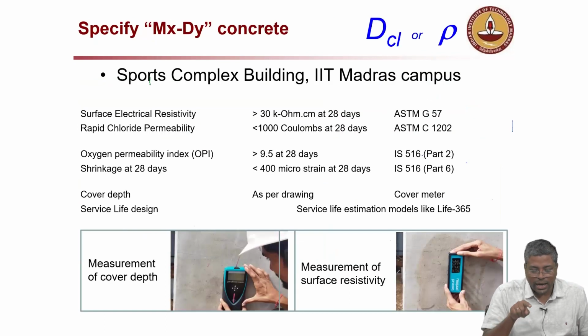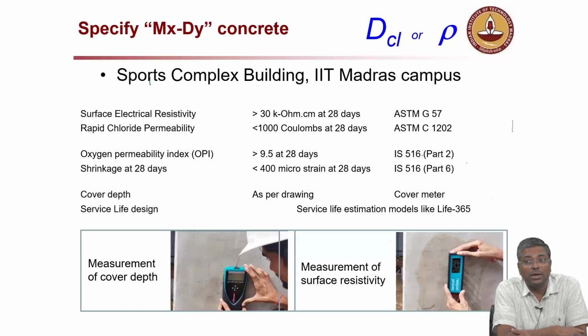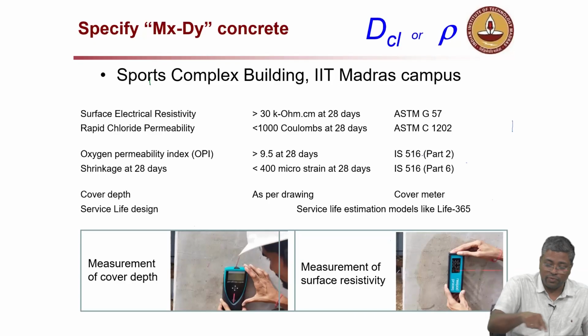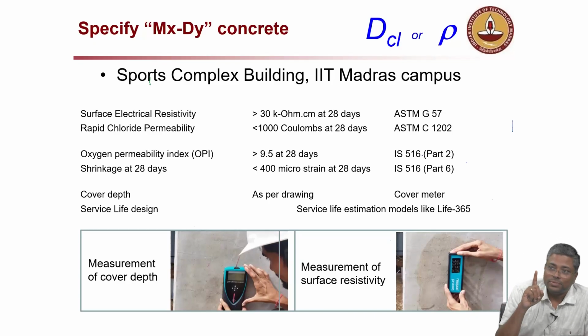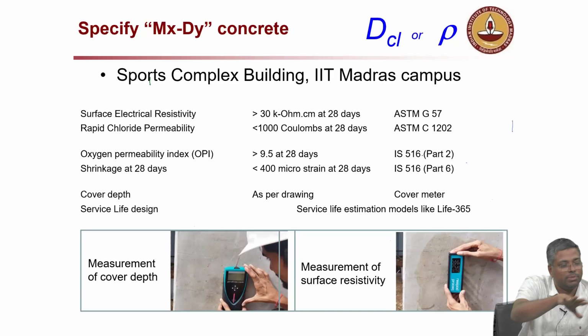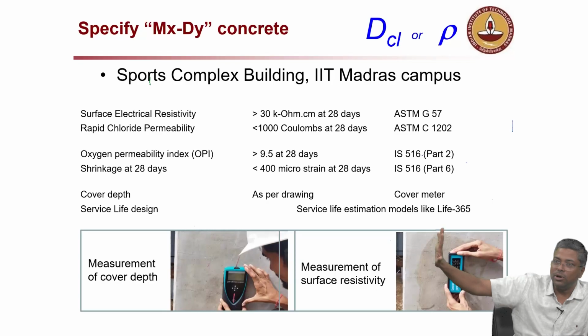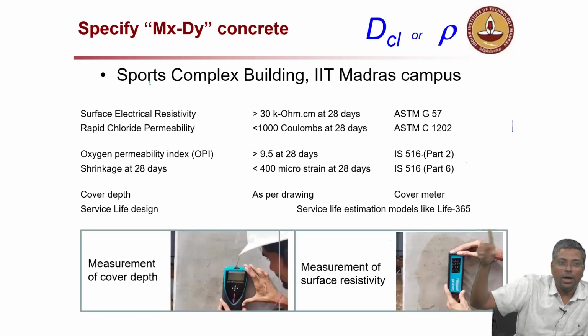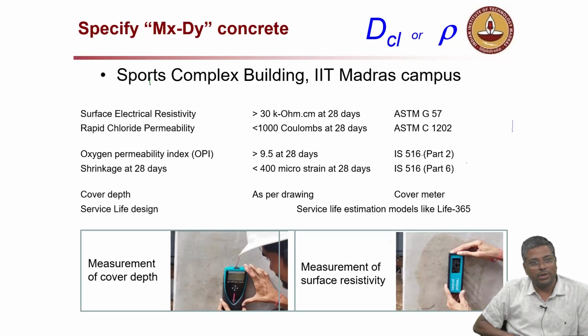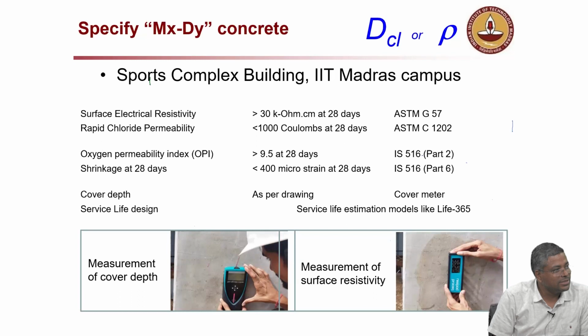Now, I think I have another slide to show this from the sports complex where we visited. Here we put it in the contract document that the resistivity should be 30 kilo ohm centimeter. Okay, the first row over there. Now there is a catch here. If you say only surface electrical resistivity, people will take measurement on dry concrete. For a cube it's okay, because when you do the compression test, a wet cube is coming, so it's fine. But if you want to use this for measurement on the actual structural element, you have to ensure that it is wet. Otherwise, if it is dry, you will get a very high resistivity value. So it may be wise to say wet surface resistivity, rather than just saying surface resistivity.